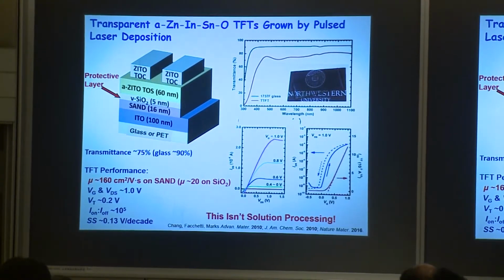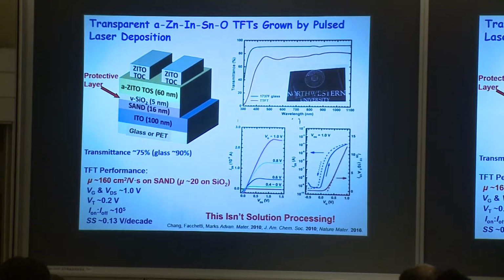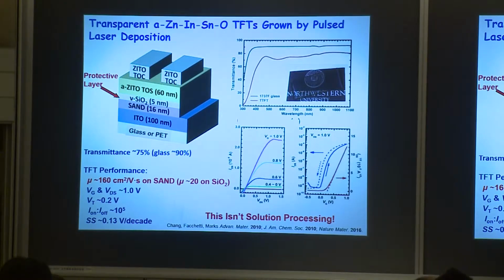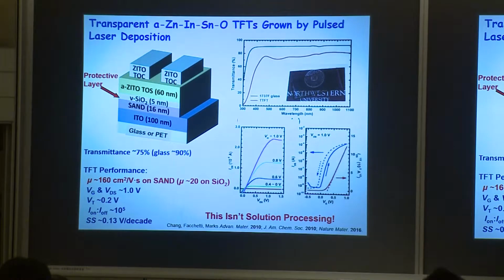So let's make a transistor. And this we did with my colleague Bob Chang. So here's the gate, or here's the substrate. It can be glass or plastic. You grow ITO on it, and there are different ways to do that. We'll talk a little bit about that, and then here's our SAND gate dielectric, and a little protective layer, because we're going to put the amorphous zinc indium tin oxide down by pulsed laser deposition. So that little protective layer is just to protect from the laser plume.